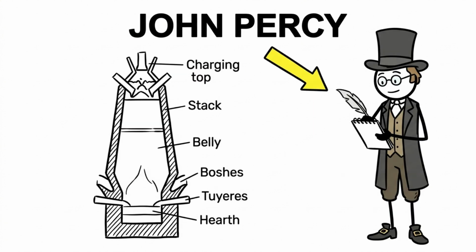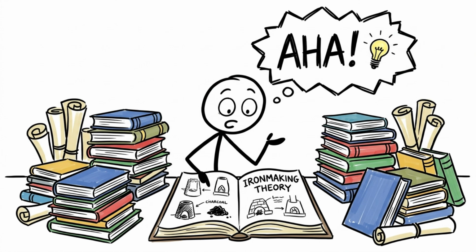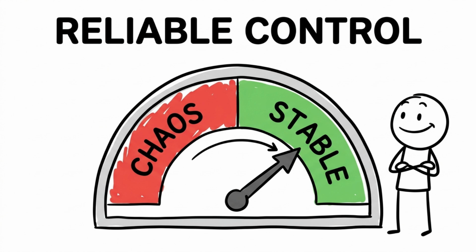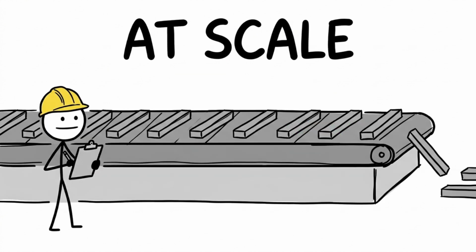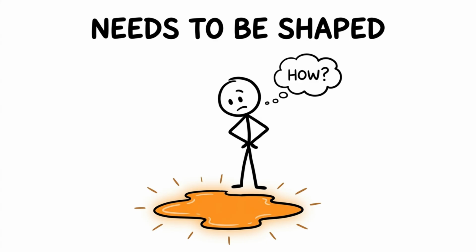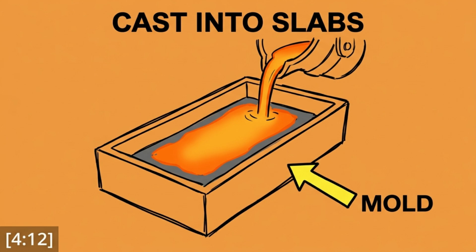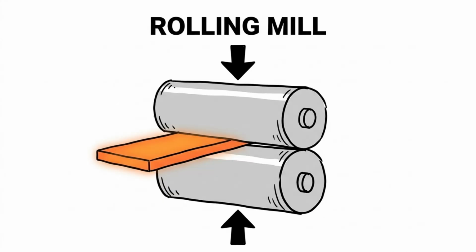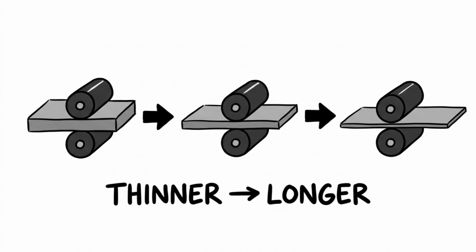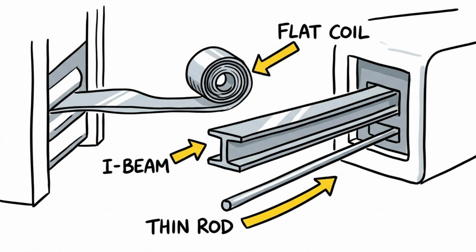Researchers like John Percy, the 19th century metallurgist whose work on iron-making laid the foundations of modern steel-making theory, spent entire careers trying to understand exactly what was happening inside these furnaces. The control their work unlocked allowed steel to be made reliably at scale for the first time. But the steel is still liquid. It needs to be shaped. The molten steel gets cast into enormous slabs weighing over 40 tons. These get reheated and passed through rolling mills. Pairs of giant steel cylinders pressing together with immense force, squeezing the slab thinner and longer with each pass. It emerges as coils of sheet metal, structural beams, or rods depending on the final product.